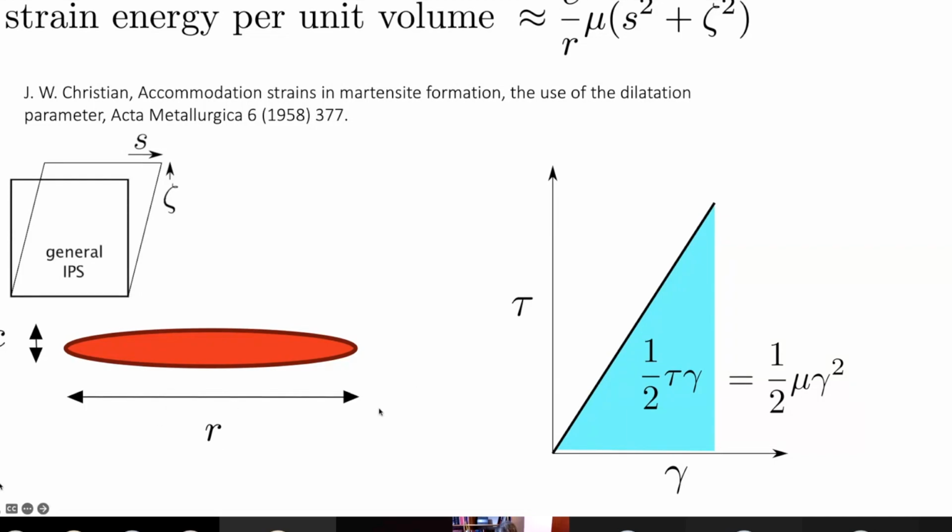So if you assume that the length of the plate is given by the mean linear intercept of your austenite grain size, and you know the chemical free energy change, you set it equal to this, then you can calculate the thickness, set this as the austenite grain size, and use 0.26 and 0.03, and you'll be able to work out the thickness of the martensite plate, as long as you can work out the driving force for transformation using one of the Calphad methods, which are so popular in the University of Udine.